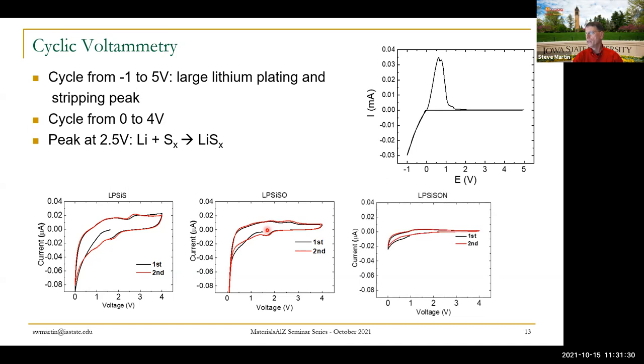Then when we go to the oxysulfide nitride, we've really flattened that curve out. We were in the microamp range, and if you look at this, we're actually down into the nanoamps. And that's the kind of stability that we need for long-term plating and stripping and battery performance. So just a note to those in this area, when you see these milliamp types of scales, everything looks flat on a milliamp scale.